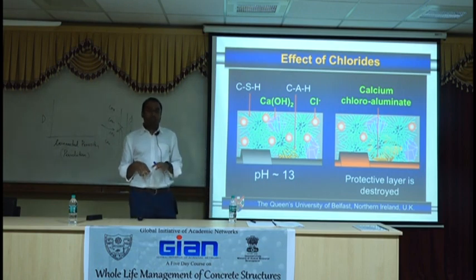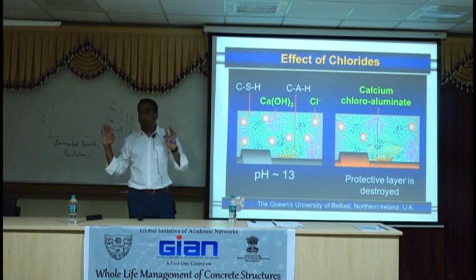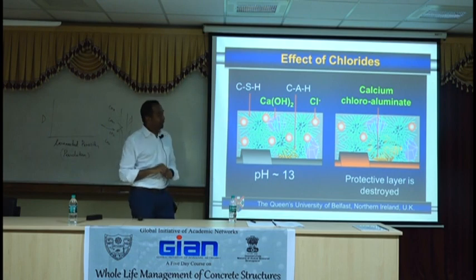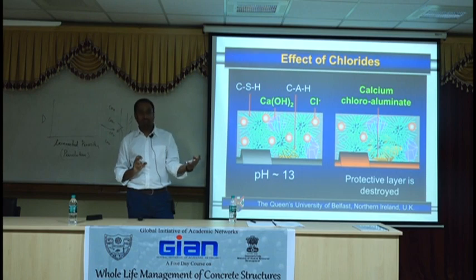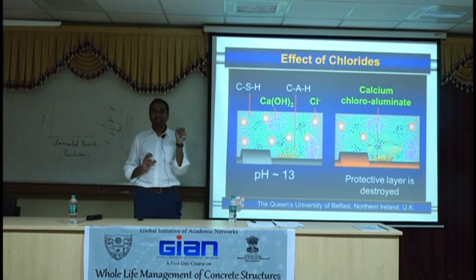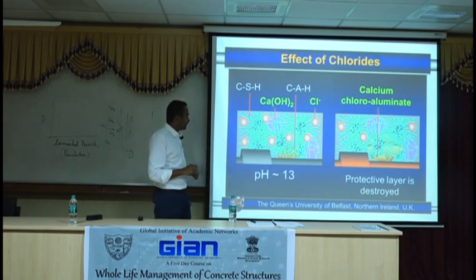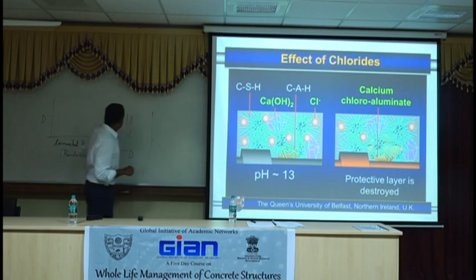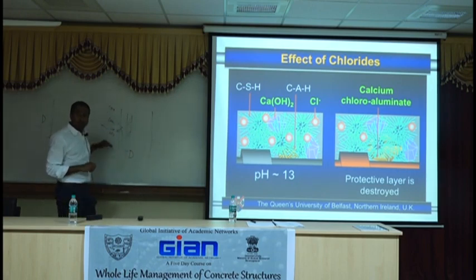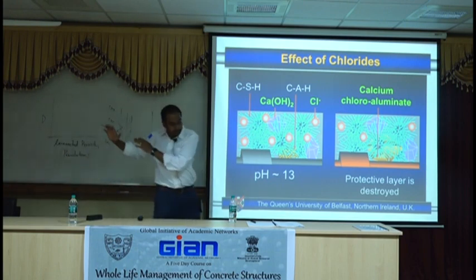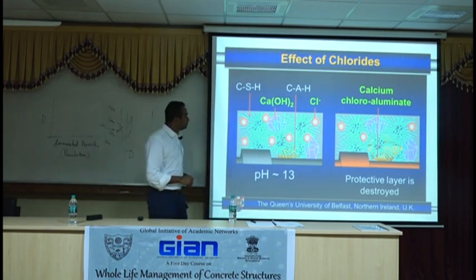But the best thing about concrete is concrete doesn't mind chlorides. It has nothing to do with chlorides. It comes in, it reacts with concrete. It is a good reaction, a good relationship between the two. So there's nothing in chloride that will affect the concrete. It's not the concrete that's the problem. The problem is the steel within does not like chlorides. So same mechanism here. It's the number of chlorides on the outside and the lack of chlorides on the inside that creates a concentration gradient. It's that driving force. It pushes the chlorides in,